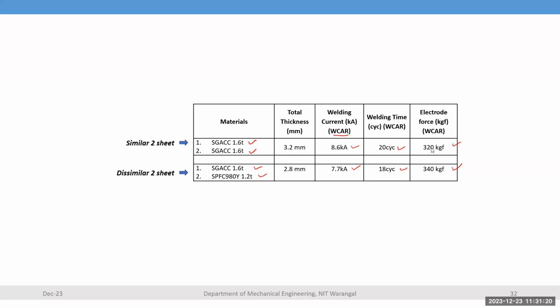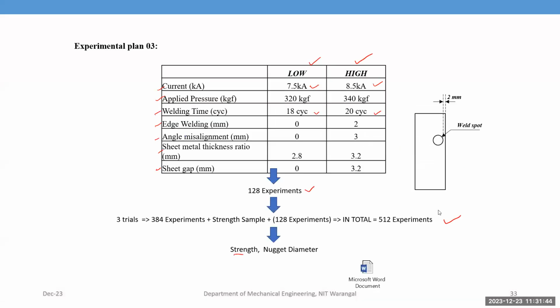Then how much force is required? 320 kg force and 340 kg force are required. So these are the variables: the minimum is 2.8 and the maximum is 3.2, and here also 7.7 and 8.6, 18 and 20, and 320 and 340 kg force. So this is the experimental layout: welding current, applied pressure and welding time, and edge welding 0.